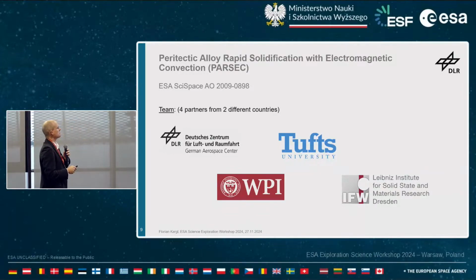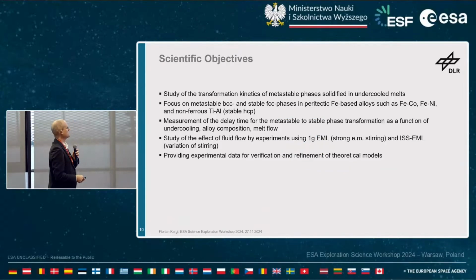The second project is called Parsec, alloy rapid solidification with electromagnetic convection. What I will focus on here is the study of the transformation kinetics of metastable phases solidified in an undercooled melt, with a particular focus on metastable BCC growth in iron alloys, such as iron cobalt and iron nickel, and a stable FCC phase that grows after the BCC phase, and in particular the transformation kinetics of that. So the key parameter here is the so-called delay time, and one can have a look at the delay time as a function of undercooling, alloy composition, and melt flow. And again here the interest is in the effect of fluid flow by experiments, comparing the 1G EML data with strong stirring and ISS EML data with a variation of stirring.